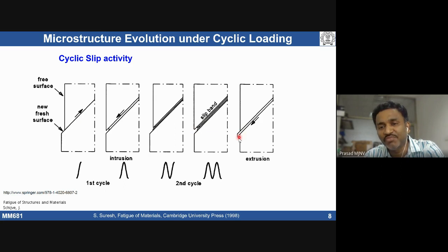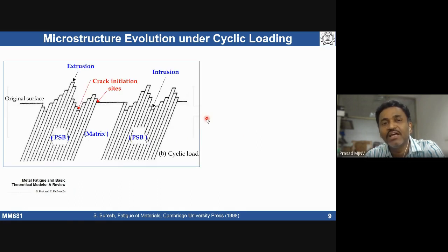If these things form, then locally it acts like a void. This can act as a stress riser for further cracks to initiate. So whenever there is cyclic slip activity in the material, that can lead to formation of intrusions and or extrusions, depending on which direction the shearing activity is happening, under cyclic deformation. Those now become crack initiation sites. They act as stress risers in the material.